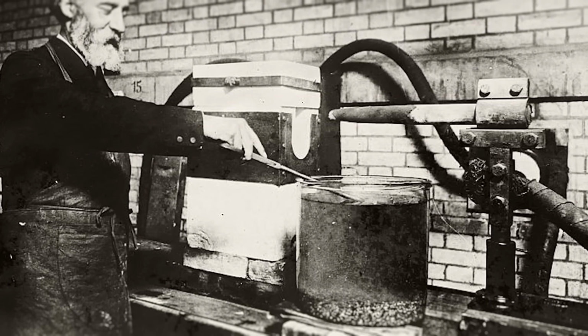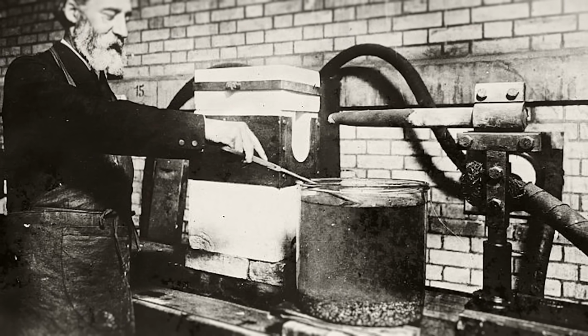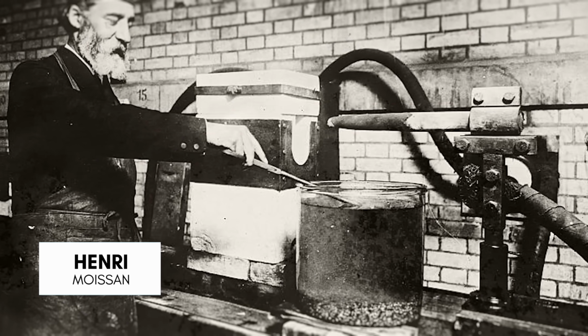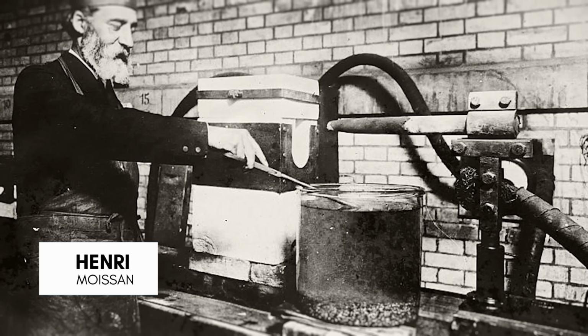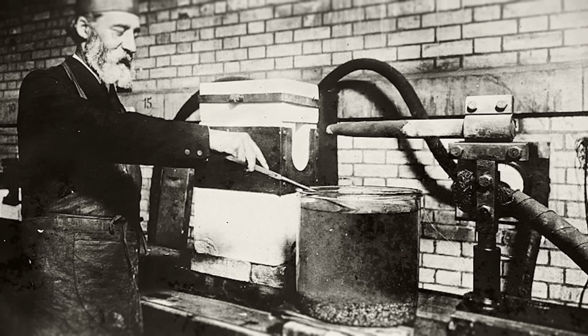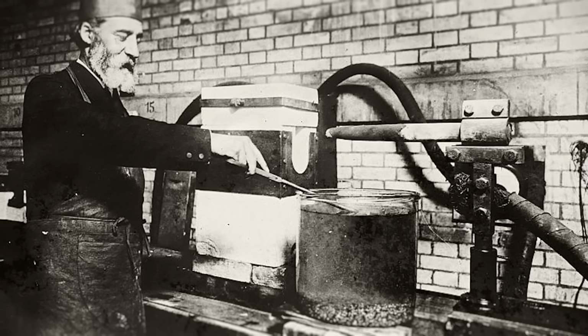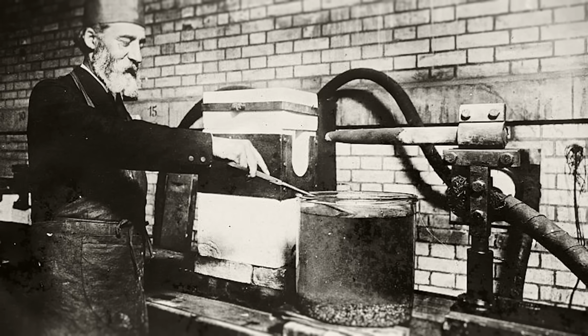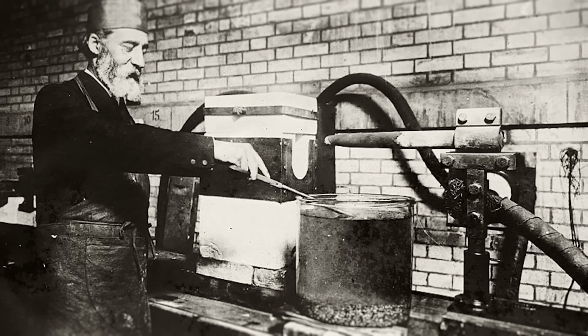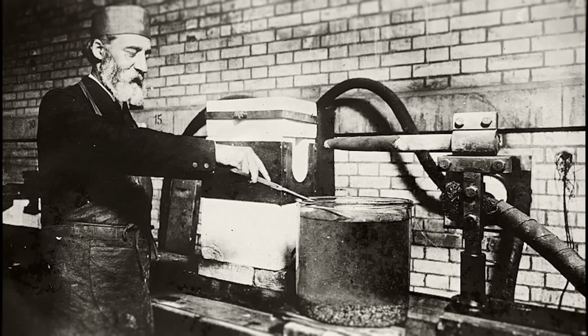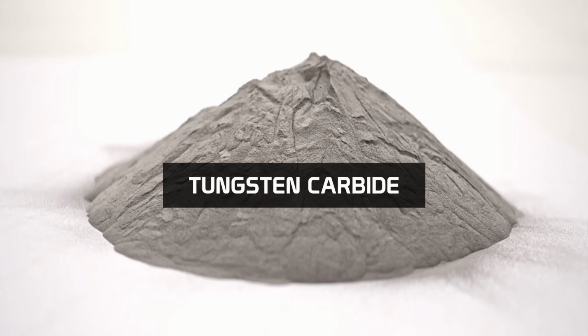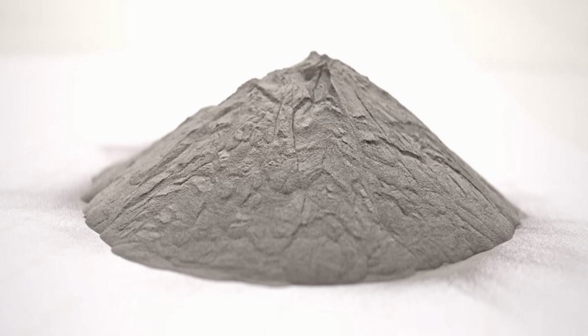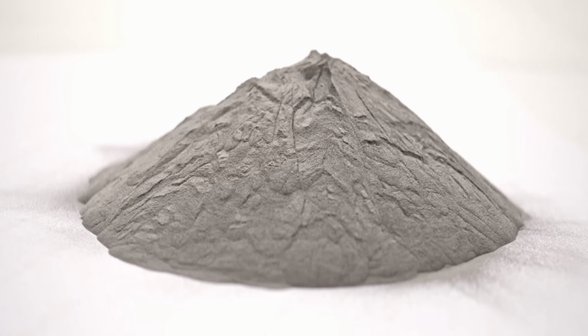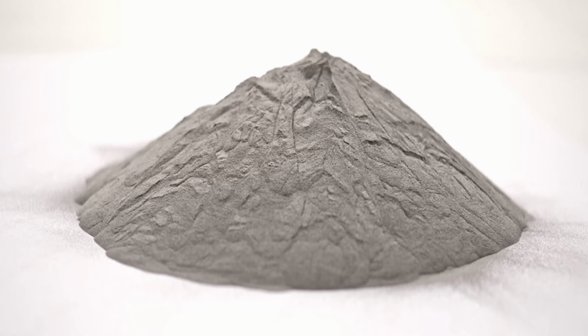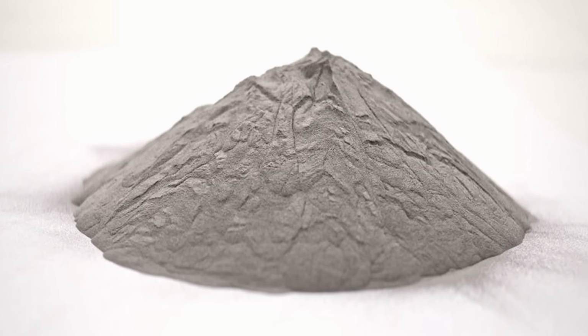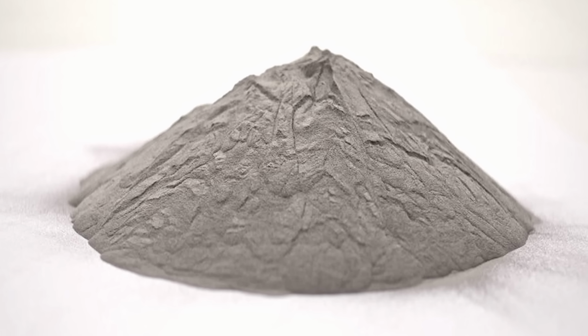The next major advancement in cutting tool design got its start in 1893 by Henri Moissan during a search for a method of making artificial diamonds. While charging sugar in tungsten oxide, he melted tungsten subcarbide in an arc furnace. The carbonized sugar reduced the oxide and carburized the tungsten. The material produced was tungsten carbide, and it was extremely hard, approaching the hardness of diamond and exceeding that of sapphire. It was also almost 16 times the density of water. Despite these properties, it was extremely brittle and had very little industrial use.